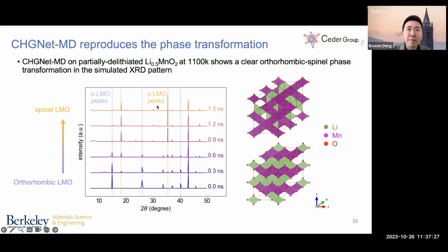To investigate the mechanism behind this phase transformation, we applied the pretrained CHGNet to run NVT molecular dynamics simulations on a partially delithiated Li0.5MnO2 cell at elevated temperatures for 1.5 nanoseconds. And the simulated XRD pattern from the snapshots in the MD shows a clear transition from the orthorhombic phase to the spinel phase, with the decrease in the 15 degree peak and the increase in the 18 degree peak.